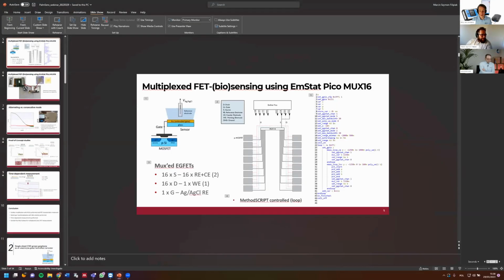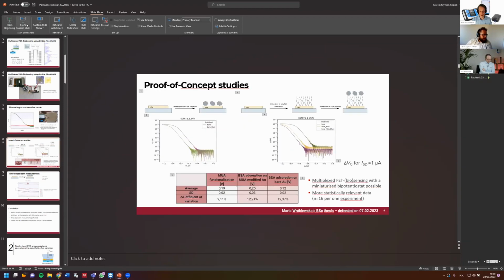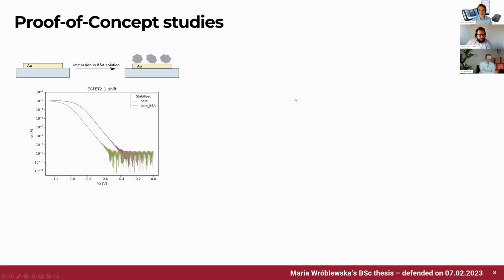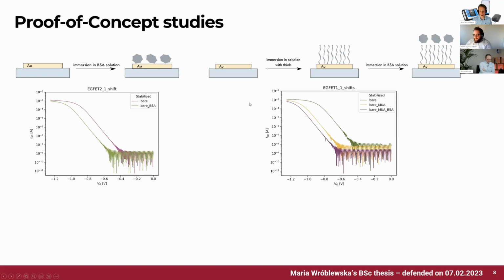And if you could go to slide 8, Marcin? Yes, of course. There are two questions there as well. The first one is, what is the thickness of the gold layer? So I normally use glass substrates, and on glass substrates, I first sputter or evaporate 10 nanometers of titanium as the adhesion layer, and then on top of that, about 100 nanometers of gold, so that it's completely covered and homogeneous, and there's only gold at the surface, and it's continuous, so to say. There are no pinholes and so on.